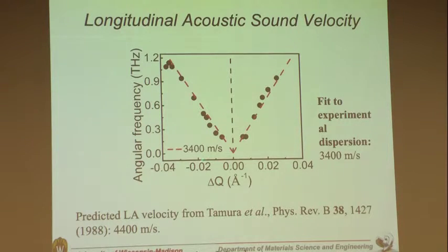You can do this, you can fit it, and you get a speed of sound of 3,400 meters per second. There's already a little bit of a surprise there, because if you predict the longitudinal acoustic velocity for systems like this using a simple composite model, you get the wrong speed of sound. So this is already information, and we think it has to do with how things are bonded at the interface. All right, so we went back and we did this again,